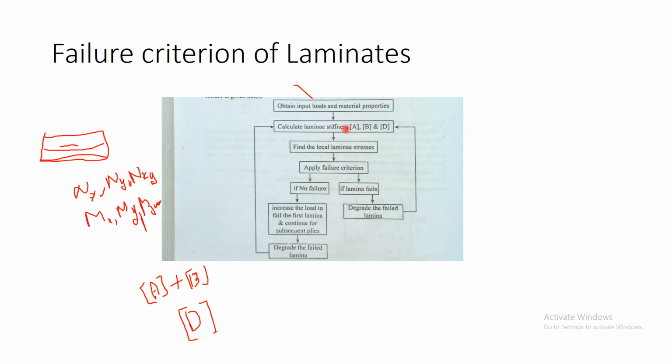So once we calculated the laminate stiffness characteristics, which depend on the load parameters N and M, I can calculate the strains. From the previous figure, I can calculate the strain epsilon and the curvature K, since we are well aware of N, M, and the ABD matrix.